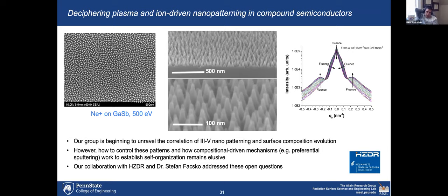Those are great questions, Feifei. Let me answer the first one. We have seen differences in irradiation. Certainly as you change the species and the charge state, you can influence the way that the structures change in terms of size and shape. What's also interesting is that you don't get patterns for all conditions. So for example, you can reach smooth surfaces when you're exposed to krypton ions, as opposed to, let's say, argon ions for the same energy. So we know it's definitely a mechanism that is driven by the energy deposition density near the surface.